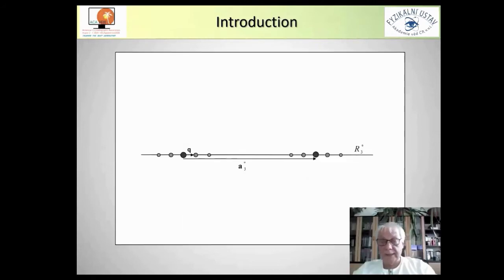Let me demonstrate the introduction of superspace for description of modulated structures with the help of a simplified model. Say that we have a one-dimensional crystal where we have main spots which are displaced by this a3 star, and we also have additional satellite spots which are displaced by this vector q. You can see that this diffraction pattern has no lattice character. To make some lattice character, we have to introduce artificially an additional diffraction vector which is perpendicular to our diffraction space.